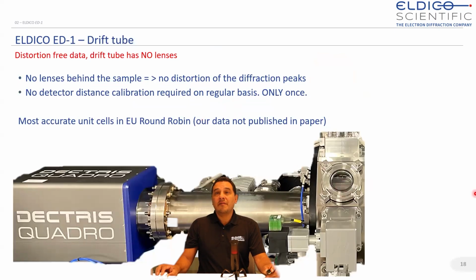And then once we have produced the beam, we hit our sample, diffraction is produced. Diffraction travels through the drift tube. And one important feature that our device has, which you cannot find in any other microscope, is the absence of lenses or condensers. Now, because we don't have lenses or condensers, we don't have any distortion that affects our diffraction peaks. And therefore, also, we don't need to constantly calibrate our detector distance. So once the distance has been calibrated the first time, the distance remains constant for the rest of the time. Because of that, and because we have better diffraction peaks, at the end of the day, what we are getting is very accurate, or more accurate, cells compared to any other device.